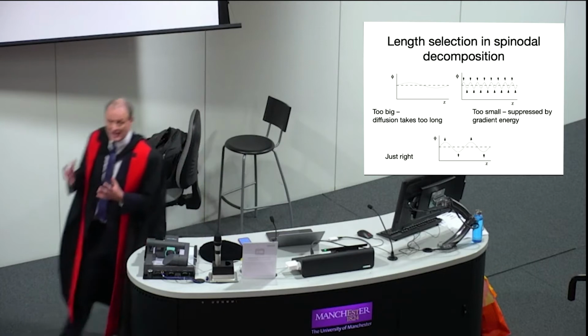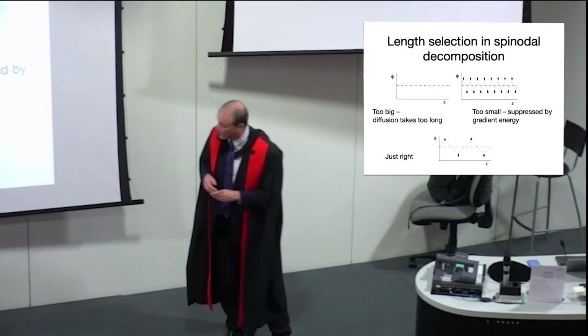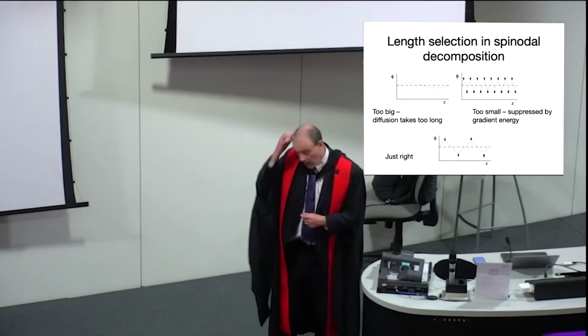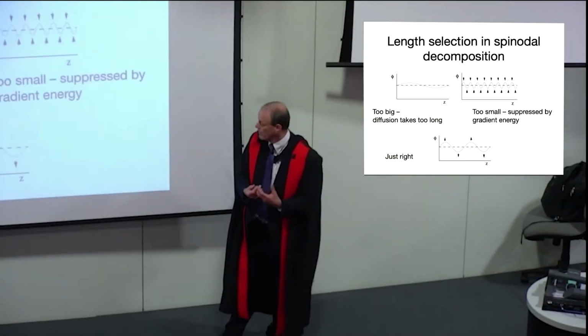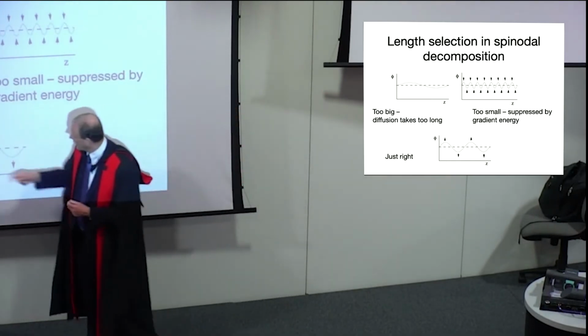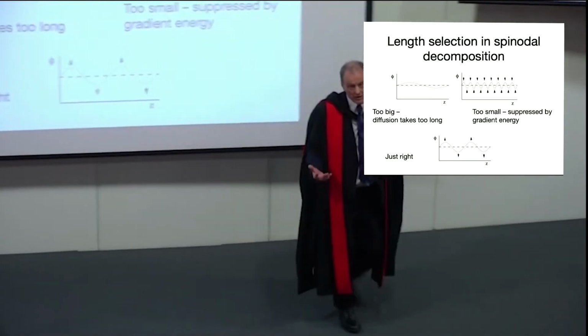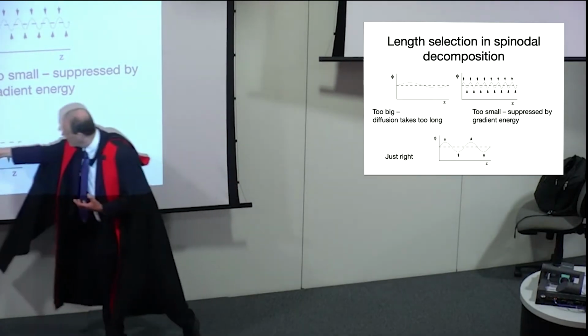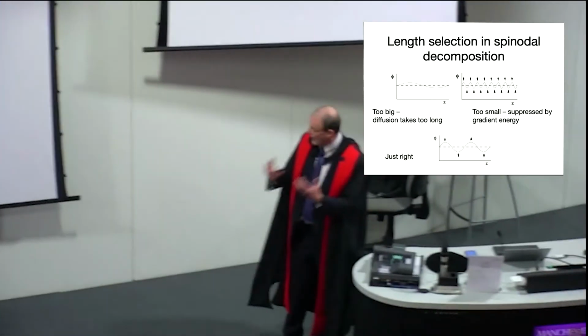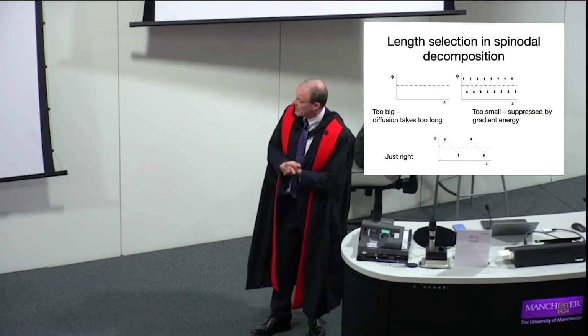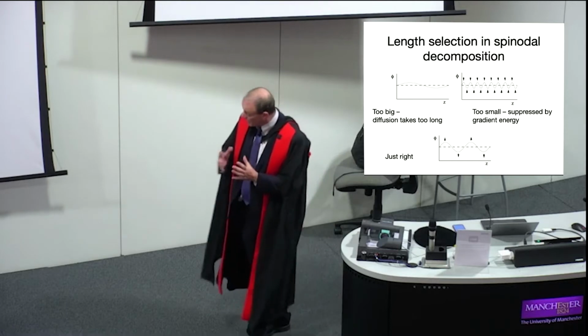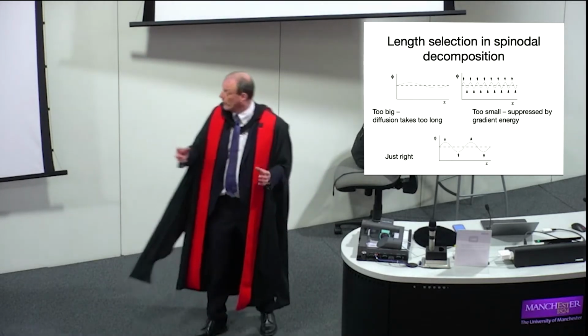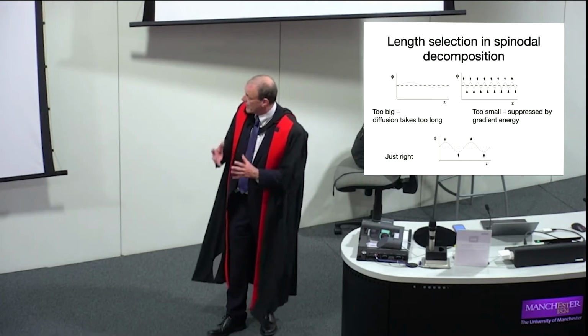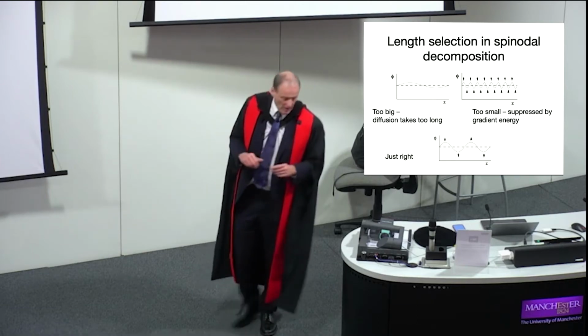And this leads to this beautiful classical mechanism that was first identified by John Cahn many years ago of spinodal decomposition. And essentially what's happening here is any fluctuation that you get in concentration, so if you start out with a uniform mixture, any concentration fluctuation you get is magnified. Imagine you get a little concentration fluctuation due to the randomness of Brownian motion, then you get a little dip in concentration, material flows from low to high, and it magnifies that concentration dependence, and that's how you get phase separation. And you get this length scale selection mechanism, which comes about because large scale fluctuations don't grow very quickly just because stuff's got to diffuse a long way. Short wavelength fluctuations are suppressed by the fact they lead to too much interface, so you get this single wavelength.